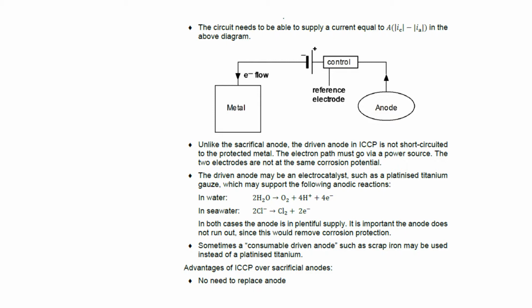If this was in fresh water, then an anode process might be oxygen evolution. In seawater, a process which happens more readily, and therefore instead of oxygen evolution, is chlorine production. This means we potentially need to be careful and avoid using ICCP in seawater if you're concerned about producing chlorine and you're worried about the fumes from that.